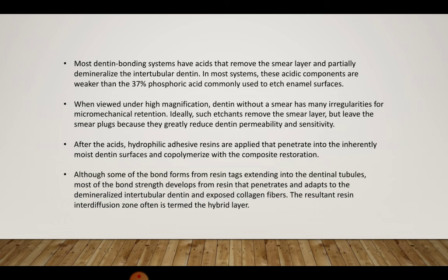Now most dentine bonding systems have acids that remove the smear layer and partially demineralize the intertubular dentine. In most systems, these acidic components are weaker than the 37% phosphoric acid which is commonly used to etch the enamel surface. When viewed under high magnification, dentine without a smear layer has many irregularities for micromechanical retention, and therefore